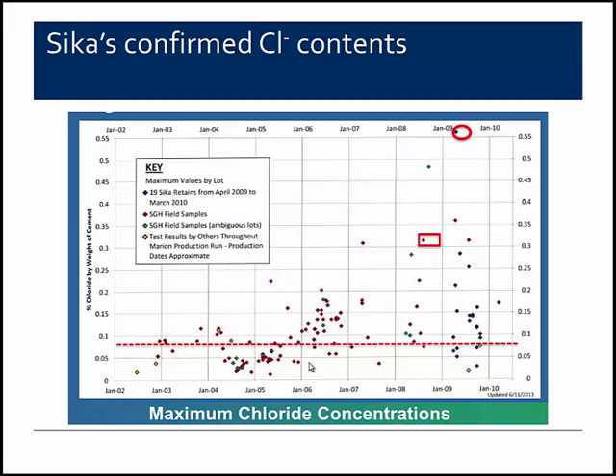This slide was produced by Sika based on the testing they did on what they call retains. So in general grout production, they have a retain sample that they keep for a period of time. In addition to the retains, SGH, who was hired by Sika to help with their investigation, actually went out and took some samples of certain bridges to try to characterize certain production time periods. And so you can see from January of 02 to roughly January of 10, all of the test results that Sika has provided. And the dashed red line there shows the specification limit. So you can see the significant number of test results that are above the specification limit for chloride content. And in particular, the oval at the top was just to make sure you noticed that there was one of them that was extremely high chloride content. The little red box was the bridge in Texas that the first chlorides were noted.